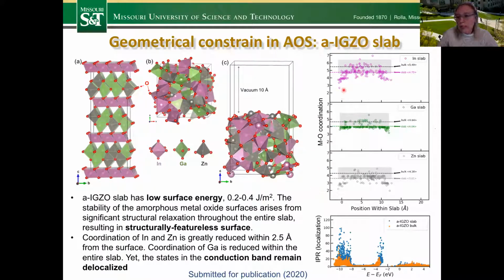Of course, the coordination is affected quite significantly. Here on the side, you can see the coordination of indium, gallium, and zinc, and especially in indium and zinc, the coordination is significantly lower when we come close to the surface. Within 2.5 angstrom, the coordination drops significantly. Here, the shaded region is the coordination range in bulk, so no surface effects, just the amorphous bulk, and the average for the bulk and for the slab.